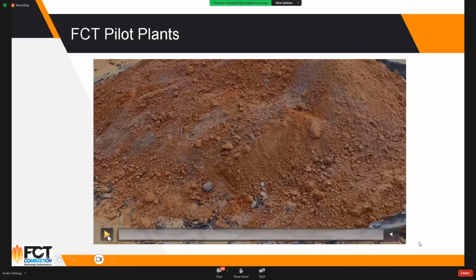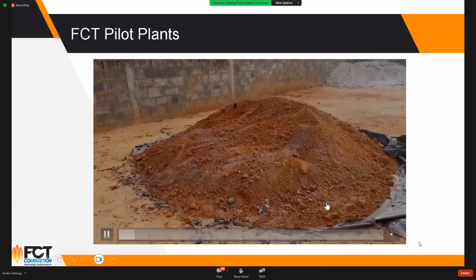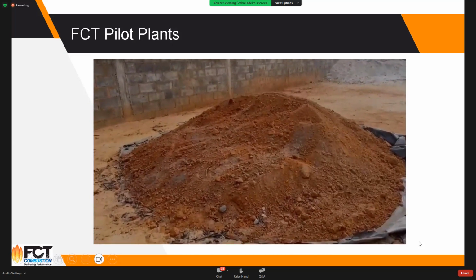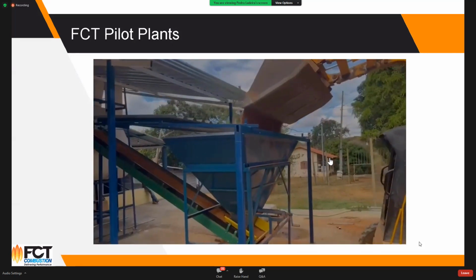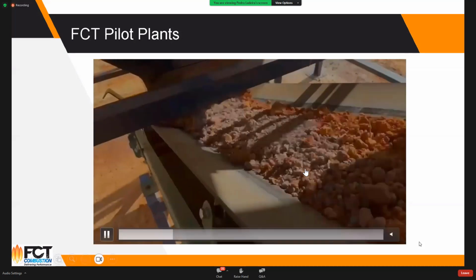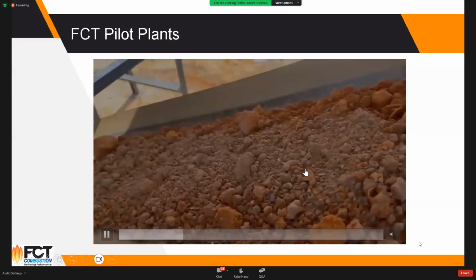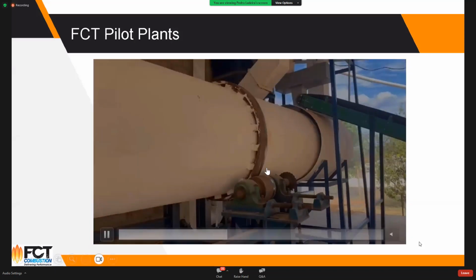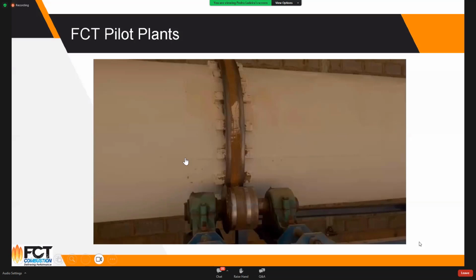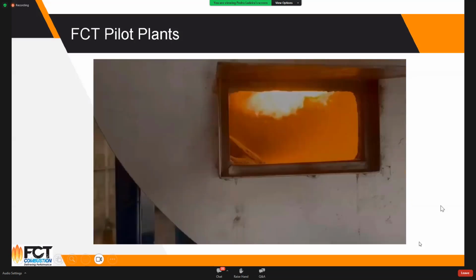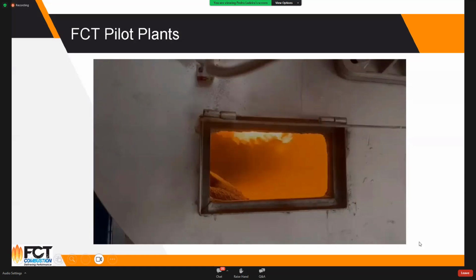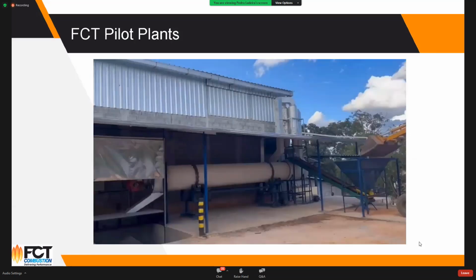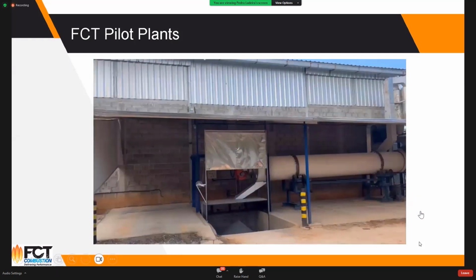This is a quick video showing the utilization of inorganic modifiers. You simply mix the inorganic modifiers along with the feed, and you can see here the material is not even ground. It's just volumetrically added to the feed. It's being processed in the rotary kiln at very high temperatures. And this one is fired with diesel, with high oxygen content in the kiln atmosphere, so there's no oxygen control or any depletion of oxygen here. But as you can see, the product becomes gray because of the reaction between the inorganic modifier and the clay. So we succeeded in doing the right color control.